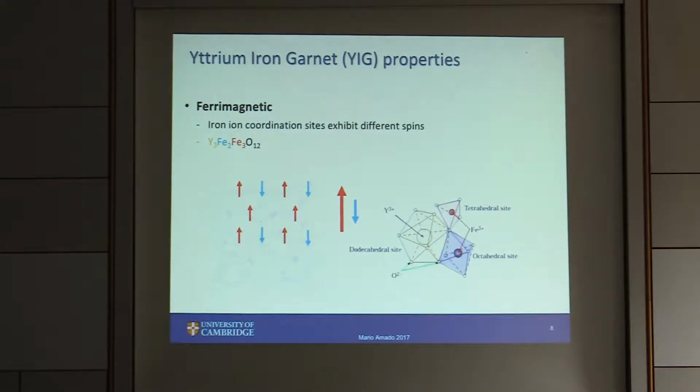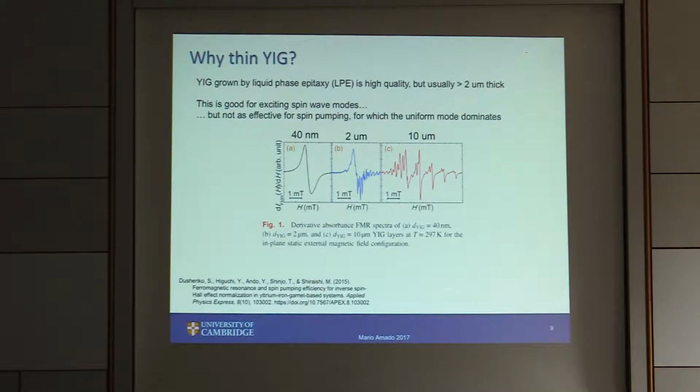So instead of having an antiferromagnet with compensated planes on growth, what we have now is uncompensated planes on the z-axis. It's a pretty nice material for ferromagnetic resonance because the line width of the magnetic resonance is extraordinarily low. The damping parameter is quite low as well. It's a high Verdet factor material and is extraordinarily insulating. Recently, last week, I think, a paper appeared on arXiv saying that it's not really an insulator. So it's a semiconductor with an extraordinarily large band gap, but we can treat it as an insulator for the time being.